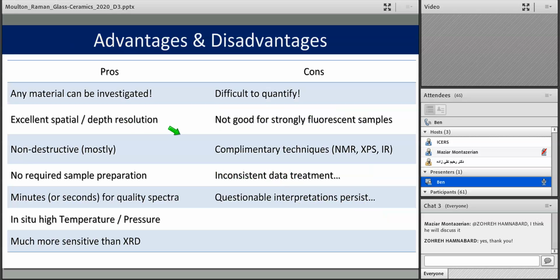At the end of the day, the advantages and disadvantages of Raman spectroscopy are the following. Almost any material, glass, liquid, gas, solid, can be studied. It has, with a very short amount of time, excellent spatial resolution, lateral resolution on the micron scale, and depth resolution of several tens of microns, usually. It's non-destructive, so long as your laser power isn't too high and you don't have a lot of absorption. You won't damage your sample.